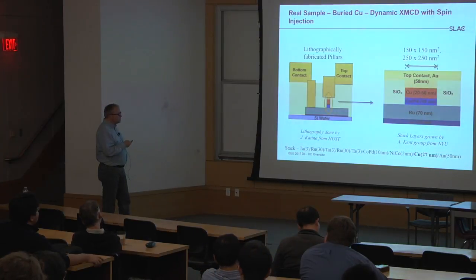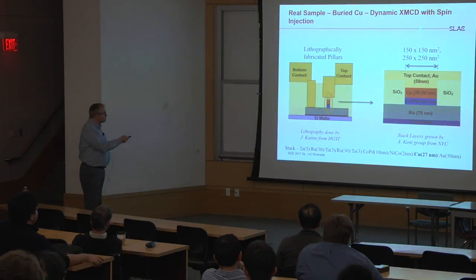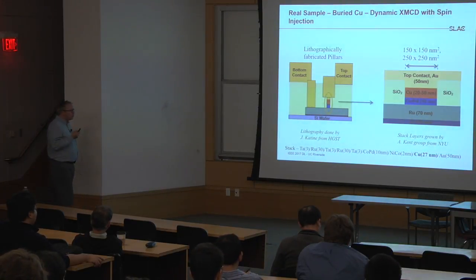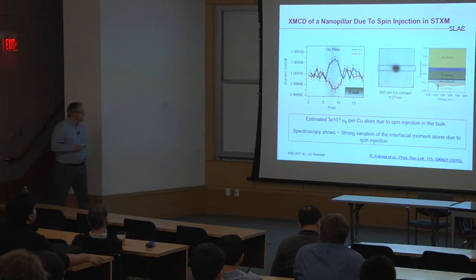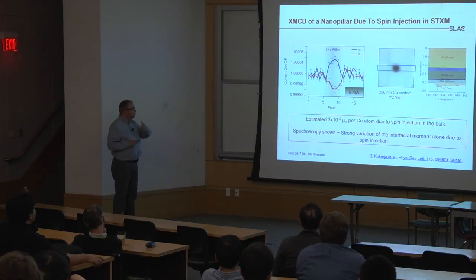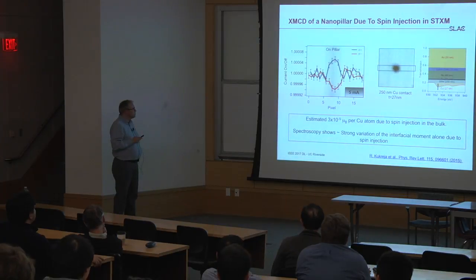And so we are monitoring the X-ray transmission through this layer, once with the current on and once with the current off, and we compare these two constantly. That allows us, like in a lock-in technique, to see how the transmission in the copper changes. These changes are very small, and that's why we do this kind of lock-in technique. For 700 nanoseconds we apply the current, then we remove the current, we apply the current, we remove the current. 700 nanoseconds is exactly how long one turn of the synchrotron takes.